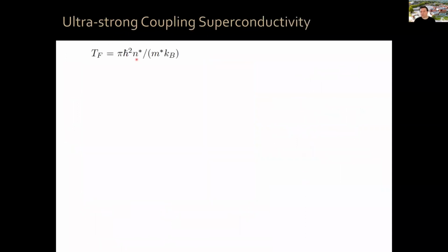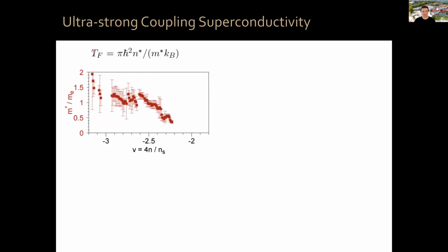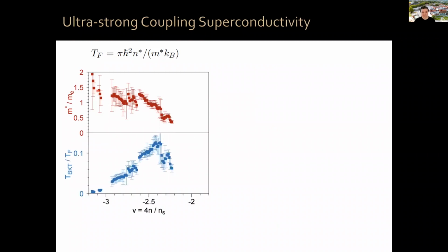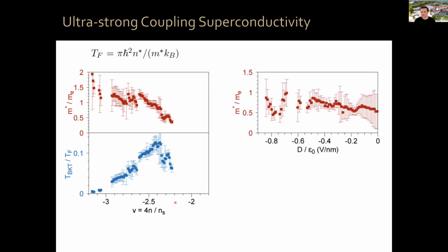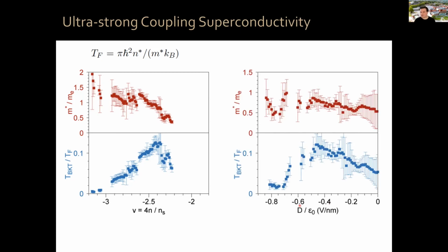Because we measure the electron density in our system and also the effective mass, we know what's the value of our Fermi temperature, okay? This is the measurement of the effective mass of our electrons as a function of filling, okay? Because we have also TBKT, we can divide TBKT by TF, and this is what we get for our system at optimal electric field as a function of filling factor, okay? You can do the same thing as a function of displacement field at optimal density, okay? And you have this TBKT over TF, yeah?